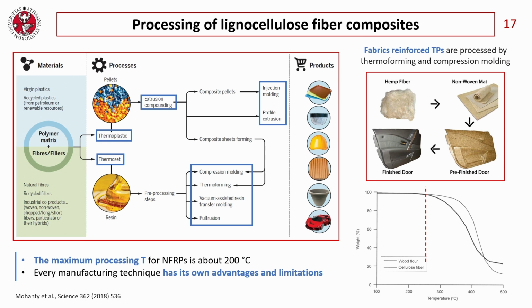An important issue, if you see this thermogravimetric chart, is that the maximum process temperature for this kind of composite is about 200 degrees. So we have a limiting temperature for these composites.